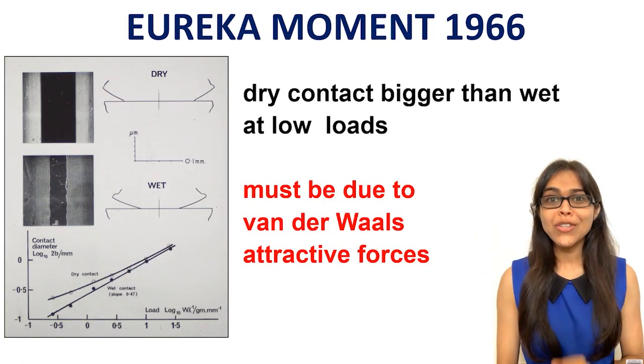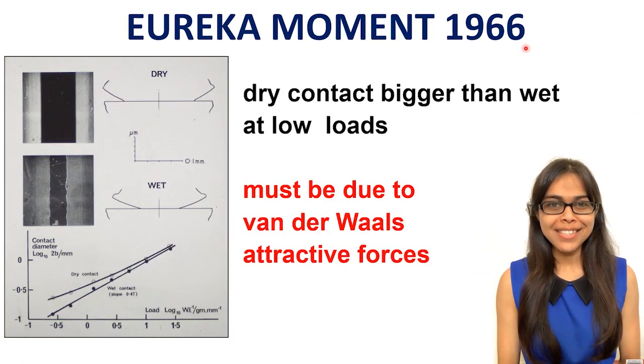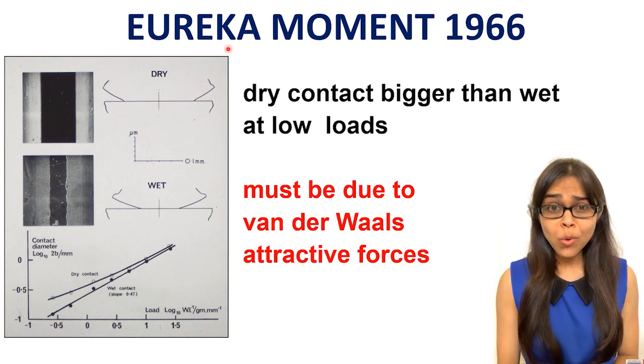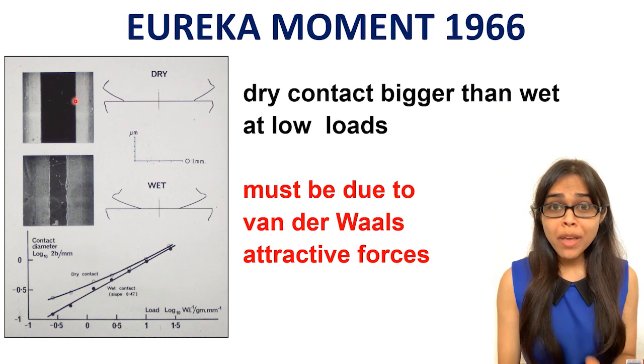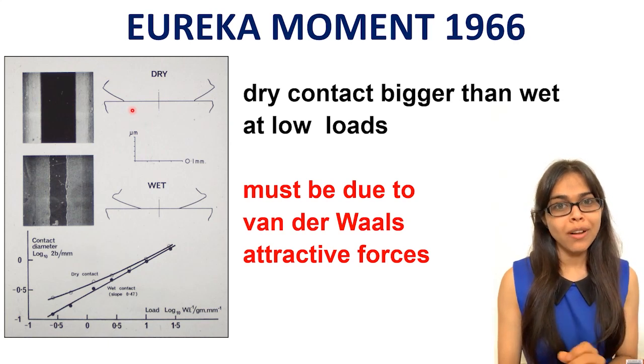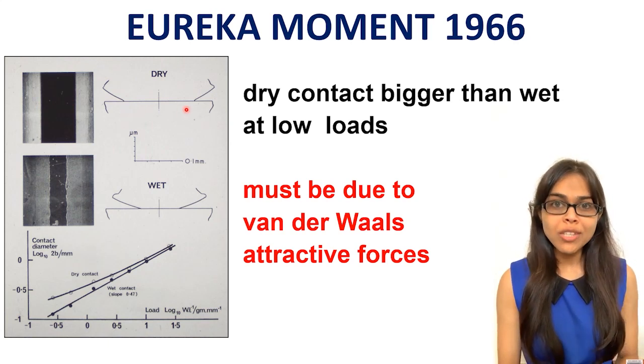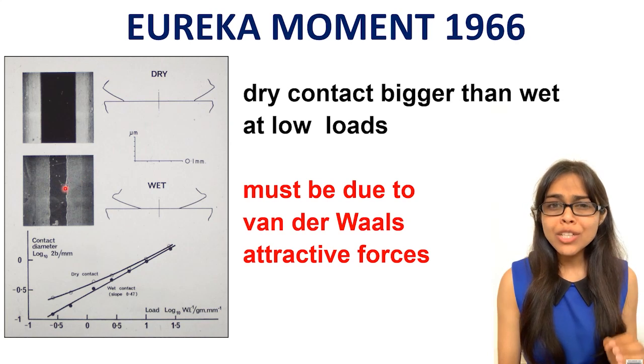That was the cause of the Eureka moment in 1966, when Alan first saw that the contact of the dry rubber on glass was much bigger than that on the wet glass. This black spot is the dry contact of smooth rubber on glass. Then in soapy water, the spot size was much smaller.